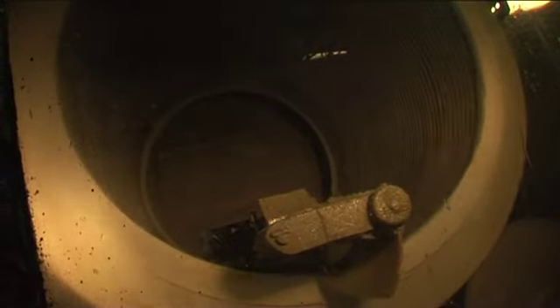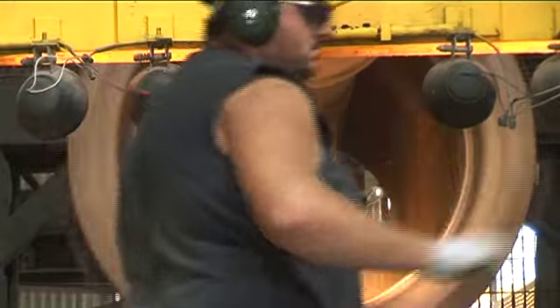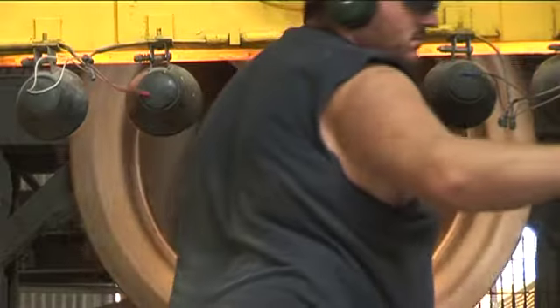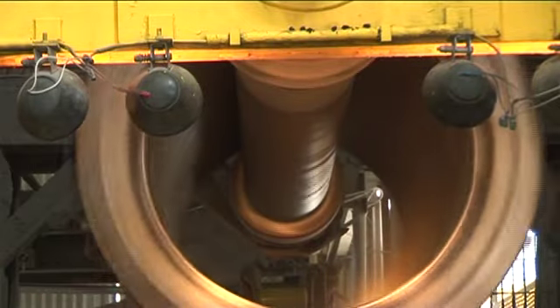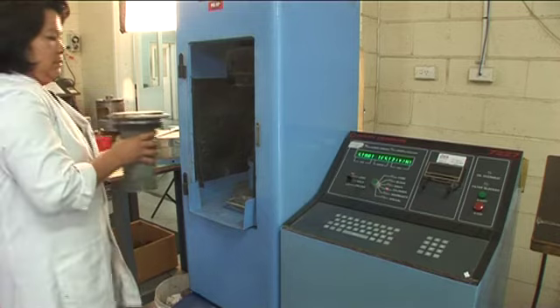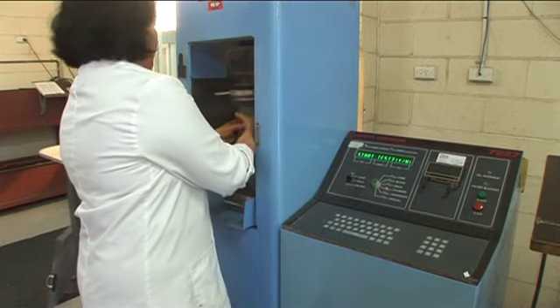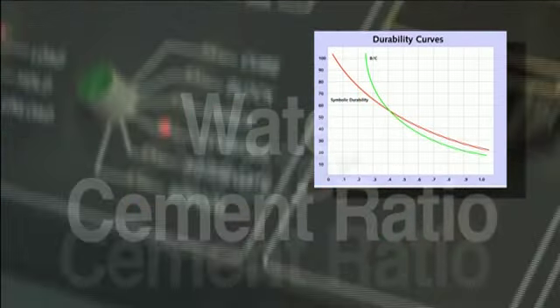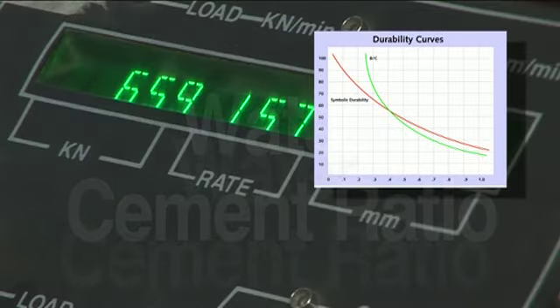The water-cement ratio or water binder ratio has a long-term effect on the durability of concrete pipe. The lower the water-cement ratio, the higher the strength, and ultimately the better the durability. Steel reinforced concrete pipe is designed to have a water-cement ratio of approximately 0.30. This allows compressive strength in the order of 70 MPa to be achieved at 28 days.